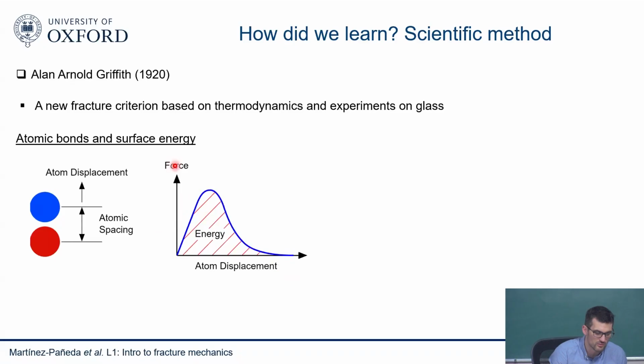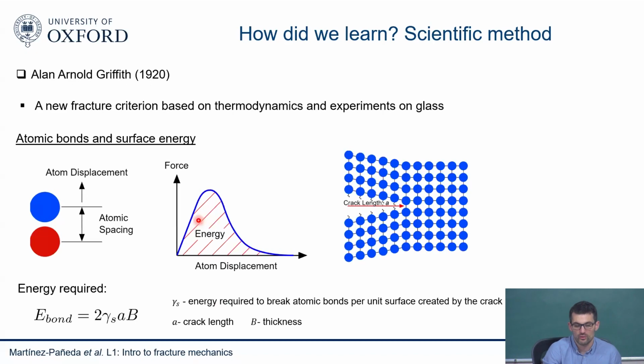And of course, if you have this force versus atom displacement, the area under the curve will give you the energy. So there's an energy associated with separating atoms. Well, if we take that approach and extend it to the general case of a material with many atoms and a given crack length, we can consider that we have many atoms that we need to pull apart. So the energy required to pull apart those atoms will be basically this, what you see here, and this will be the area required to create a new surface. And because we have two new surfaces, every time a crack grows, we have a surface on the top and another on the bottom.